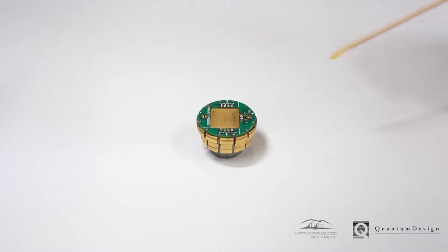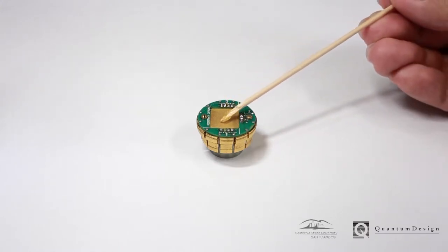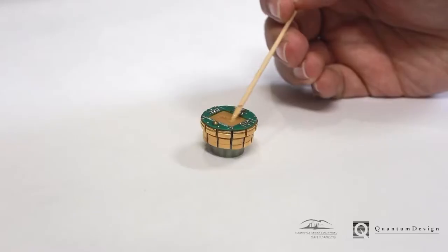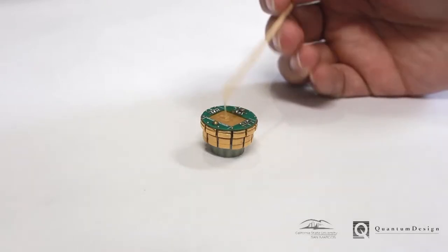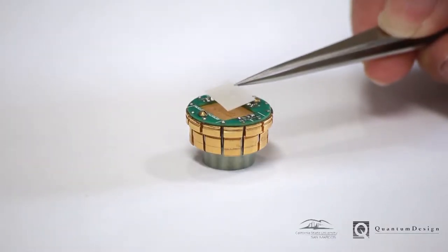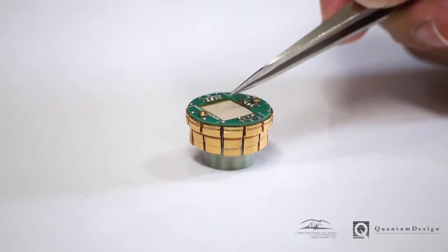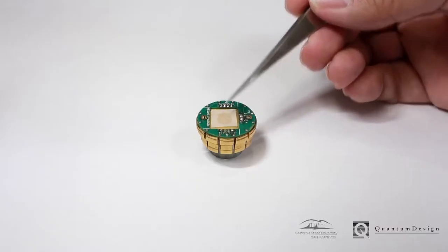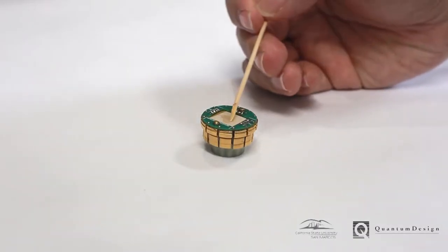Samples are mounted on the VersaLab measurement puck. When mounting samples, care must be taken to electrically isolate the sample from the center gold pad. A typical method to do this is to adhere cigarette paper using low temperature thermal grease, such as Apiezon N, in order to provide good thermal contact with the puck without shorting the sample electrically.